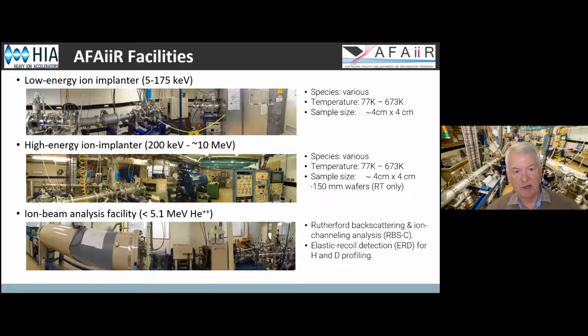It's based on 3 accelerators. We have a dedicated low energy ion implanter, which runs ion energies between 5 and 175 keV. Fairly broad range of impurities. It's a negative ion source, a sputter source, so it is more limited than the high energy implanter. But we can heat and cool samples during implantation, and again, reasonable ion currents, typically in the microamp to tens of microamp range. We have a high energy ion implanter, which takes the energy range from 200 keV up to around 10 MeV, depending on charge state of the ion.